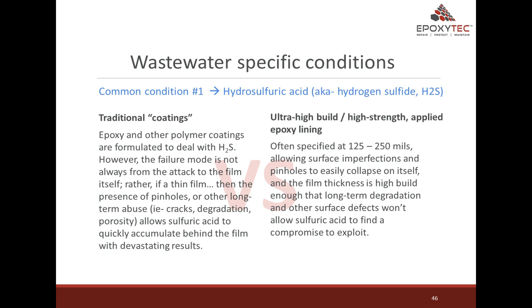Common condition number 1, hydrosulfuric acid, H2S gas, hydrogen sulfide. A traditional coating, epoxy and other polymer coatings are formulated to deal with H2S. However, the failure mode is not always from attack on the film itself. Rather, if a thin film has the presence of pinholes or other long-term abuse, i.e. cracks, degradation, porosity, it allows sulfuric acid to quickly accumulate behind the film with devastating results.